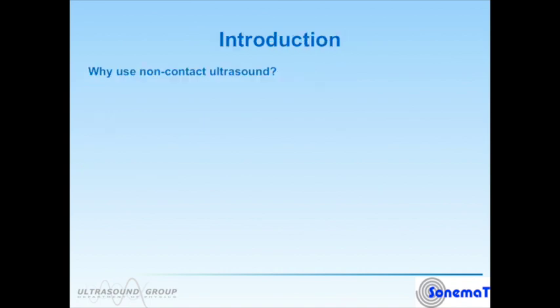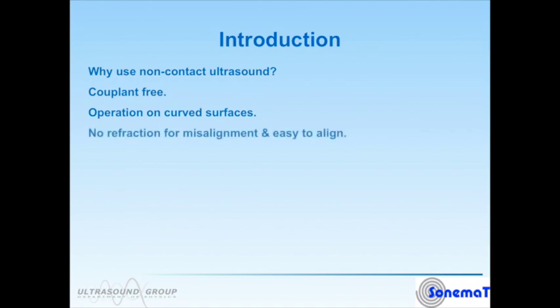So, why should we use non-contact ultrasound? The first one is obvious, it's couplant free. Something that doesn't always occur to people is that EMATs operate very effectively on curved surfaces. They're extremely tolerant to misalignment on the curved surface. This tolerance to misalignment really comes about because there is no refraction.